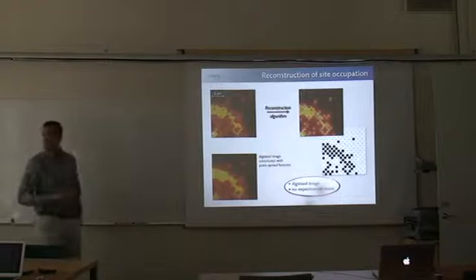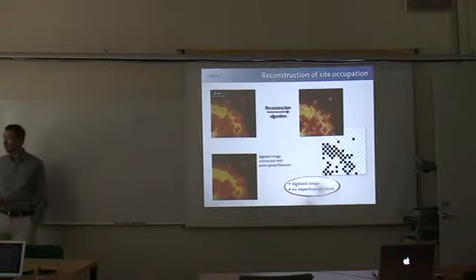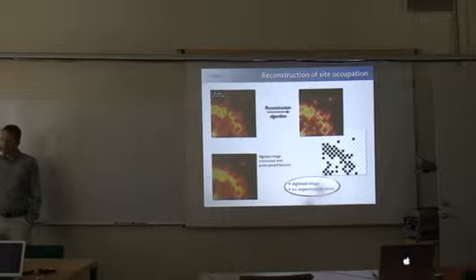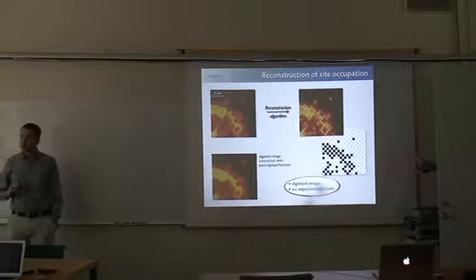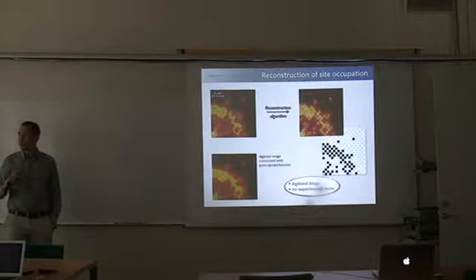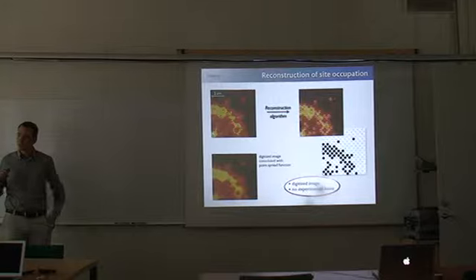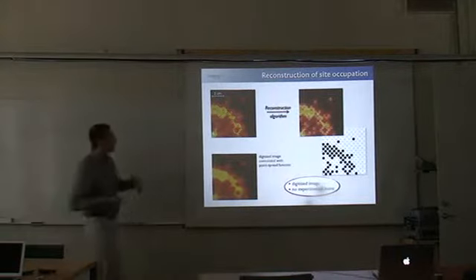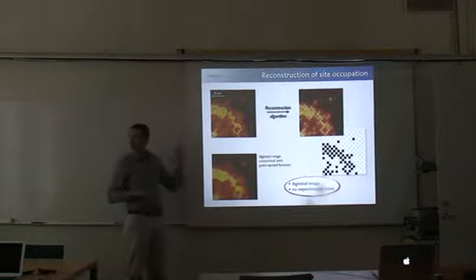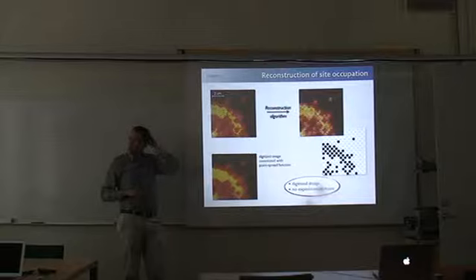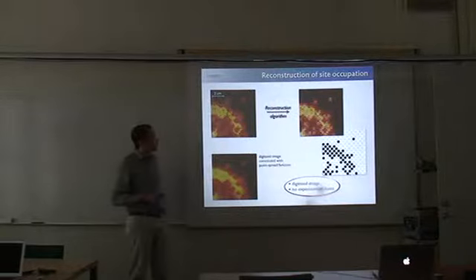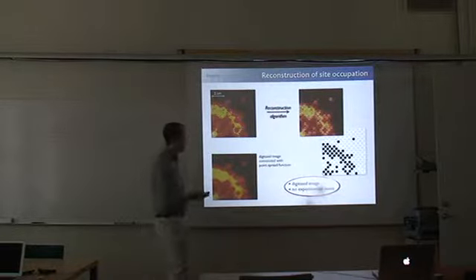Are you saying that the particle sitting on the nearest neighbor site has no contribution, or might confuse whether the second site was empty or occupied? There's no experimental resolution, we can reconstruct the distribution with 99.5% fidelity, and we check this by creating artificial images. So we start with a known distribution. No, I'm asking because sometimes you have bright yellow, then it's red, and then it's black. What do you do if it's a little bit yellow and mostly red?